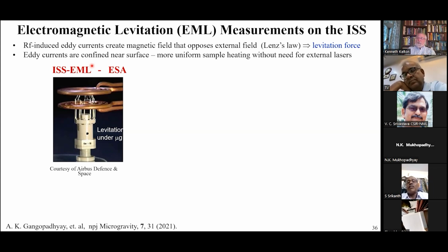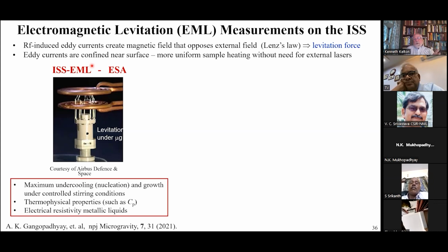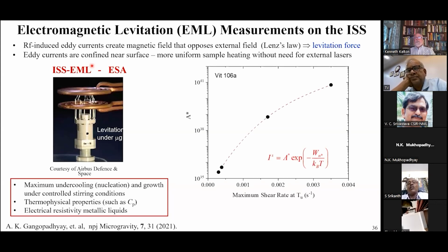You don't need much positioning force in microgravity to keep the sample. So that means you can take the sample to very low temperatures by turning down the heating. You can also increase the positioning power if you want to, and what that will do is cause the sample to stir. And so by using this, you can get controlled stirring. You can also measure maximum undercooling and growth conditions under controlled stirring. You can measure thermophysical properties such as specific heat, and you can measure electrical resistivity. The latter two have led to some very interesting observations as well, but I'm not going to talk about those here. This is the key result.